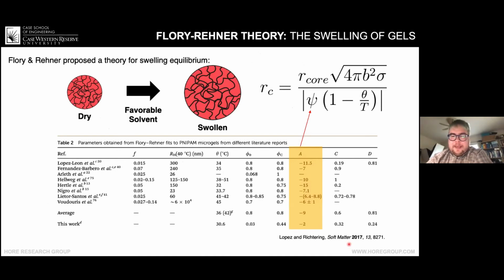This is a great paper from 3 years ago from Lopez and Richtering. And this value A is the same as psi in our expression here. And you can look at these values and see that they're kind of close to each other, but there is some deviation. And the average value that's in the literature is -9. And Lopez and Richtering went back and did a careful analysis of all the data they could find and actually found that the value was closer to -2. So here's an example of those unelucidated discrepancies between thermodynamic data in the literature.